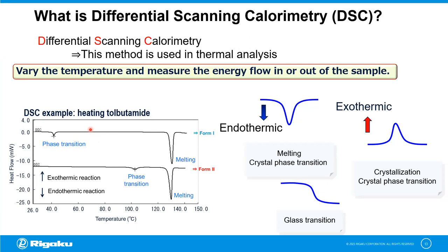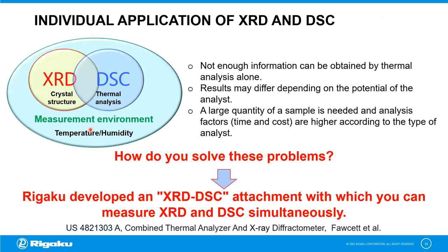What we're looking at as we change the temperature are phase transitions. A dip is an endotherm, and that means energy is going into the system. A peak is an exotherm. That means energy is coming out. So an endotherm might be a melting of the sample. An exotherm might be crystallization. A glass transition might show us a small change in the baseline. So this gives us information about what the sample does as we add or take away heat from the system.